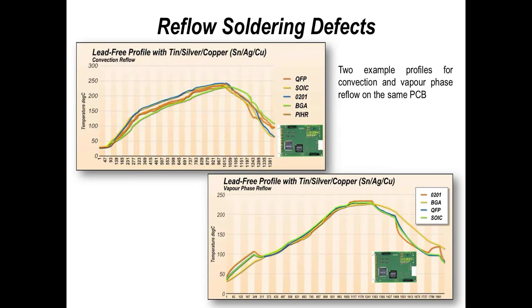It is said sometimes by some vapor phase salesmen that you don't get any differential temperature across a printed circuit board. And that's true when you get up to peak temperature where the material is condensing onto the surface. So you can get a zero difference. You will quite often monitor a difference because of the difference in calibration of thermocouple cables. That's a given. But you will always get a differential in temperature. It may be a lot smaller with vapor phase than it is with convection, and it may be also easy to run lead-free and tin lead with one material in a vapor phase system. So if you were running 230 boiling material, you could easily do tin lead and lead-free. If you were doing tin copper solder paste and tin lead, then you might have to move up to 240 boiling temperature. However, with 240, you're still pretty close to a lot of companies' profiles that they used to run with tin lead anyway, if you are honest when you talk about the peak temperatures you actually see on your products.